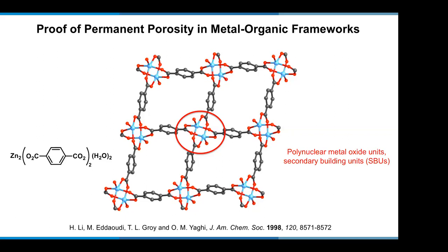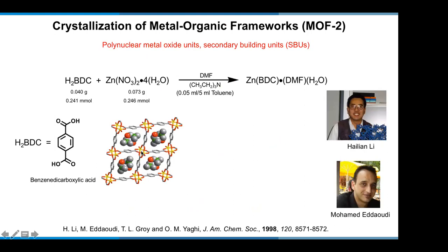It turns out this strong bond SBU approach was to be the method of choice for making the great majority of MOFs. One could almost say all the useful MOFs today are made from the strong bond SBU approach, which we developed in the mid 1990s. In this particular report, we showed for the first time that these clusters are useful at making architecturally robust systems, where the structure I just showed you has DMF molecules filling the pores.